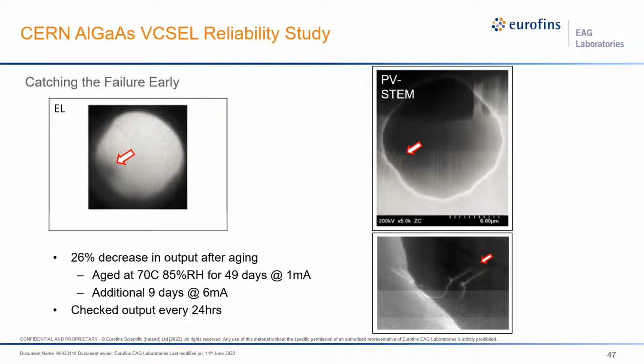This slide shows the actual effects that the defects have on light emission of a VCSEL. The image on the left is of the optical emission of the device that is just starting to fail. You can see the dark area pointed toward the left edge of the image. This is the same area. When this same area is STEM imaged in plan view, you can just start to see the defect network forming at the aperture edge. The defects are seen more clearly in the higher magnification image below it. So from the conditions used in the accelerated age test, the CERN scientists have concluded that it is very important to keep moisture out of these devices.